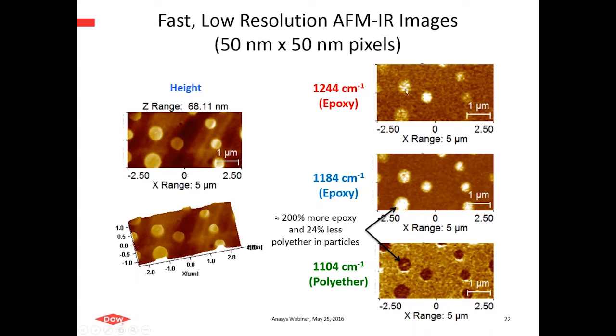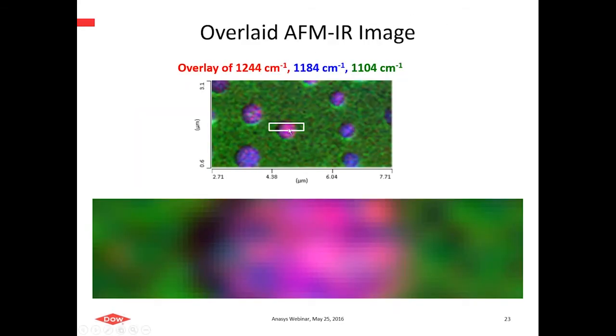And not only can we see the two different domains and something about their chemistry, we can make some estimates of compositional variation within the domains relative to the matrix. We see a clear enrichment of the epoxy feature based on the maps in these rigid domains, which we know are mechanically rigid. So we now are able to complete the story from the mechanics to the composition about what's going on in this phase-separated system. Here's an overlay map showing 2 of the bands associated with the epoxy, and one with the polyether and the matrix in green. And even with the mapping, you see that within a particular particle, there is some modulation of composition. It's based on these intensity variations. So there's some finer scale compositional variation that would be more interesting to explore as well.